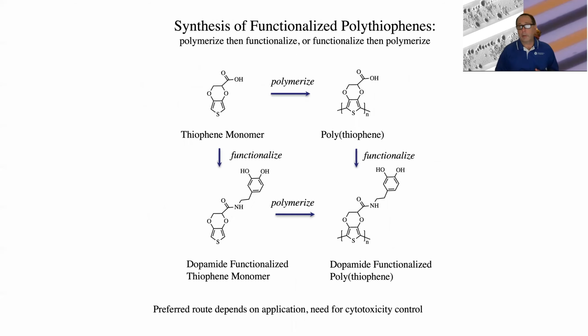So again, just to emphasize that this degree of processability and synthetic flexibility allows us to consider either making monomers into polymers and then functionalizing the polymer, or making a monomer and then polymerizing the monomer to make the polymer. The preferred route depends on really what application you're after and what the other limitations are. The biofunctionalized thiophenes tend to be less cytotoxic, but they also tend to be more difficult to polymerize because they become more hydrophilic. And so getting the polymer to crash out of solution using the electrochemistry that we prefer is more difficult when the monomer becomes more hydrophilic.